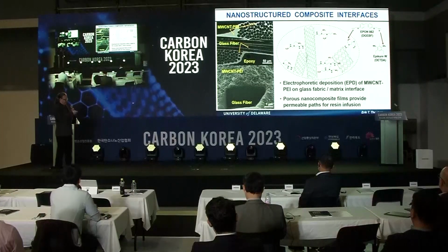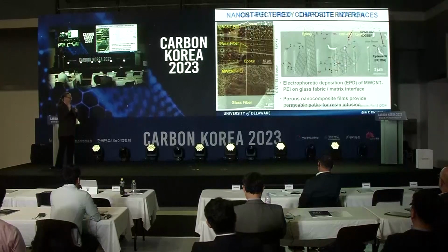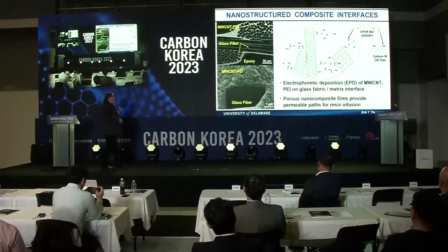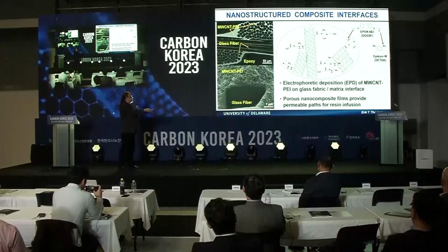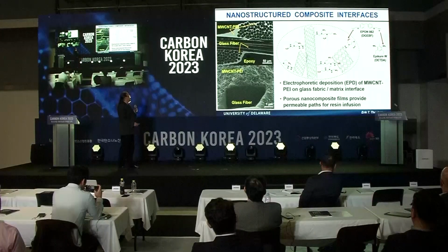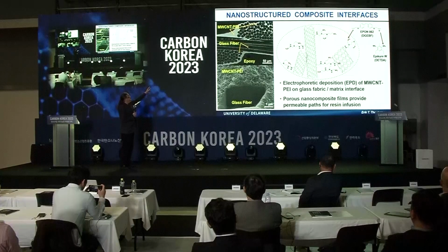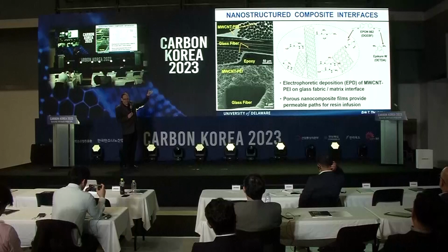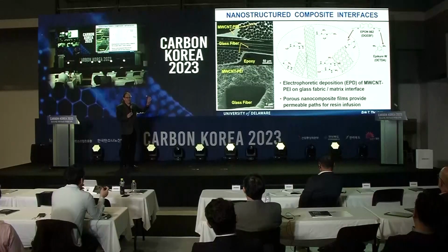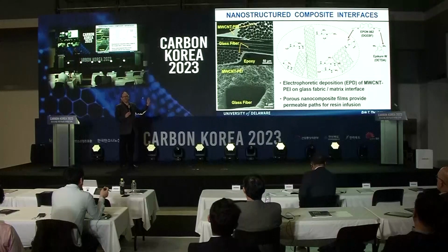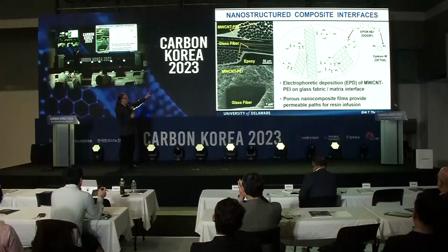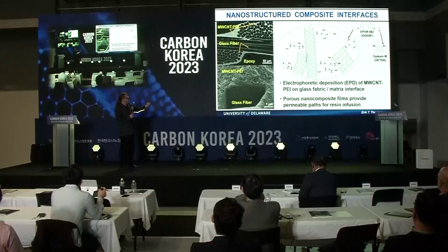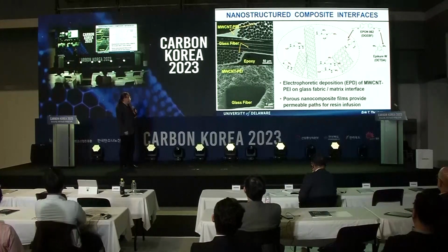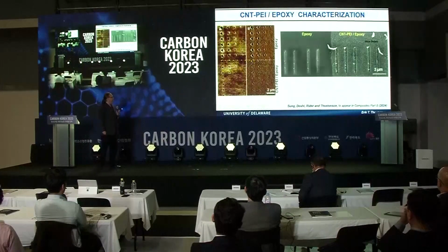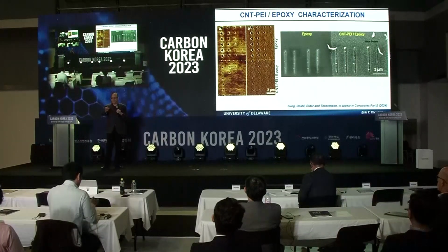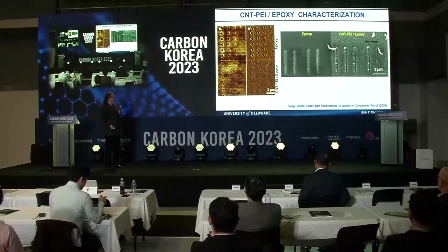What you see here on the right-hand side is a cartoon of the carbon nanotubes and the chemical functionality. Again, in the upper left-hand corner, what you see is a scanning gallium ion image. The bright areas are the regions where the carbon nanotubes are, and you can see that we're integrating those into the fiber bundles. And on the bottom, you see that porous nanocomposite coating. Certainly, it has unique mechanical properties as well as electrical properties.